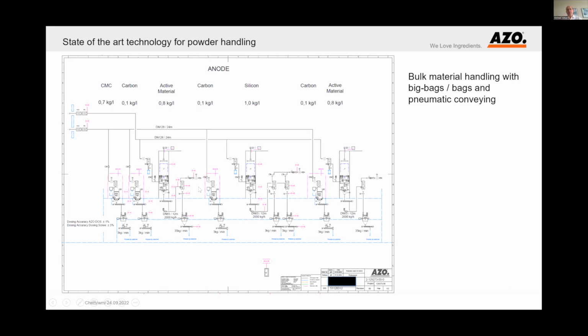And for the active materials, which are necessary in higher amounts, we usually have the big bags here. And for such a combined system, we often have a big bag station on one position, and then we have a pneumatic conveying, usually a suction conveying to a separator, and then feeding again a scale, which is feeding to the mixer, which is not shown here. So this is a state-of-the-art system, which is also used in Asia and also in the Asian companies which are manufacturing in Europe presently. And it has some advantages and disadvantages.